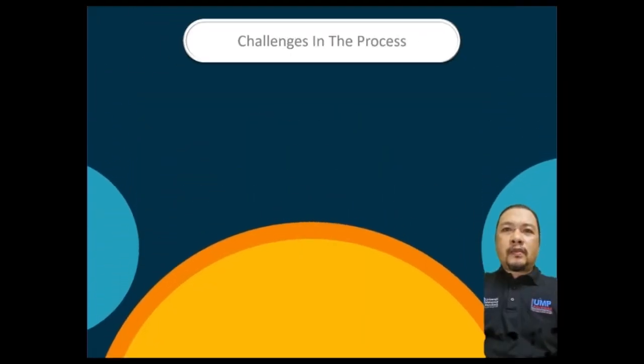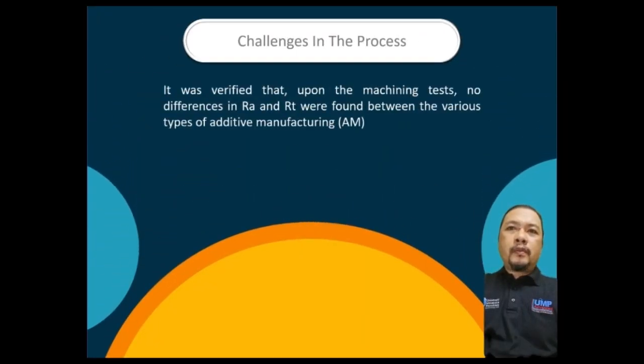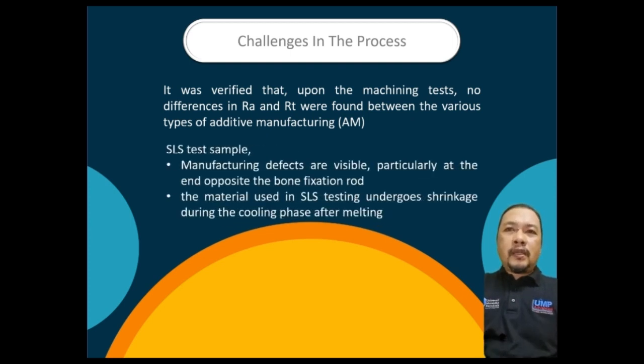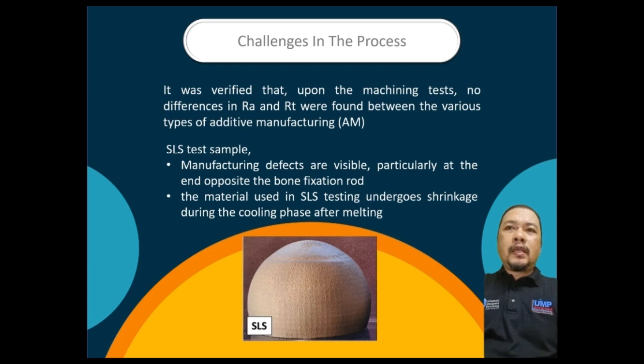Challenges in the process. It was verified that upon the machining test, no difference in Ra and Rt was found between the various types of additive manufacturing. For the SLS test sample, manufacturing defects are visible, particularly at the end opposite the bone fixation rod. The material used in SLS testing undergoes shrinkage during the cooling phase after melting.